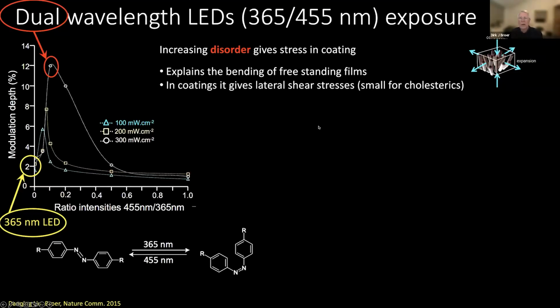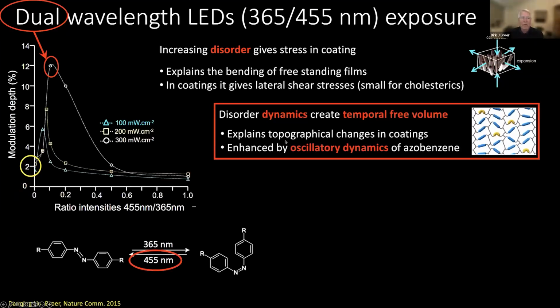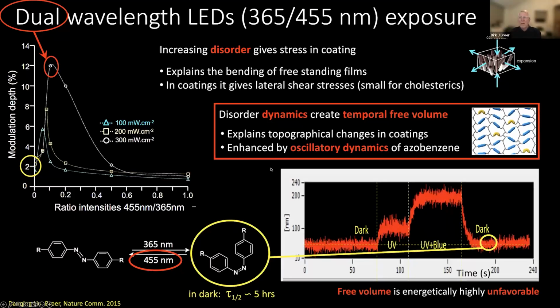But as soon as we add the second wavelength to it, then we are promoting the backwards reaction from the cis to the trans in a more dynamic way. So it always happens in the system that you have trans to cis and cis to trans formation. It is not a static system, but the dynamics of the system is actually improved by adding the second wavelength. And that oscillatory dynamics in the azobenzene basically creates the increase in volume. And that's demonstrated here once again.